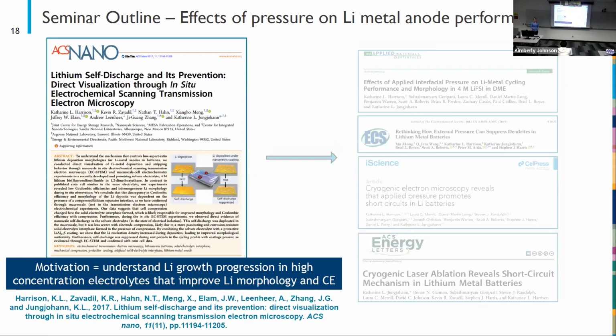So the motivation for this paper was actually not studying pressure, but it was to understand the lithium growth progression in this 4-molar lithium FSI and DME electrolyte. We saw that beautiful morphology that formed, and we wanted to understand why. How does it nucleate? How does it grow? So we wanted to do that inside of a TEM so that we could run electrochemistry and just sample images at various times as the lithium grew.